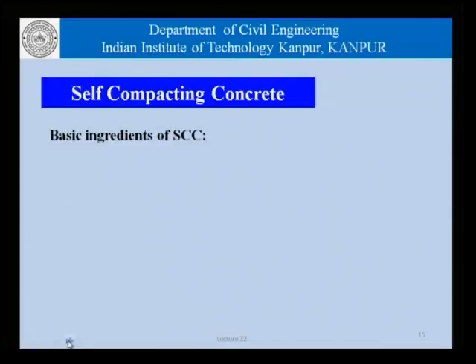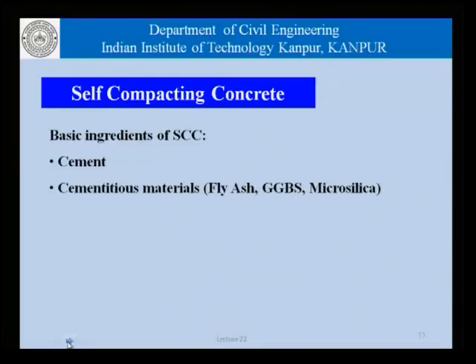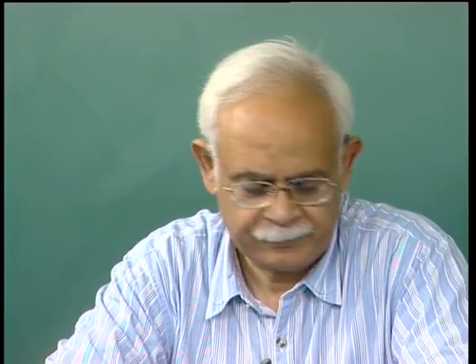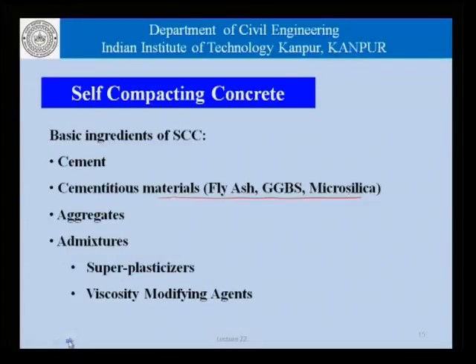As far as the ingredients of self compacting concrete are concerned, they are no different from the usual: cement, other cementitious materials, fly ash, blast furnace slag, microsilica, stone dust, aggregates which are fine and coarse, and admixtures which could be superplasticizers or viscosity modifiers. Now, we land up using a lot of these cementitious materials in self compacting concretes for the simple reason that we need to have a higher volume of paste, a higher powder content in the mix. This is something which we talked about last time, and we will look at it once again today.